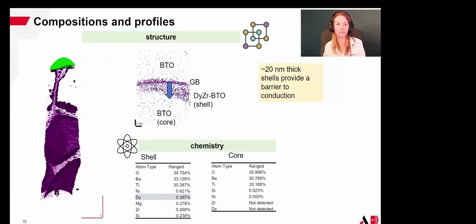We can also look at the approximate size and uniformity of this shell, and we find that it's kind of a different phase. It's still BTO, but with the significant presence of both dysprosium and zirconium. This forms about a 20 nanometer thick shell, which is sufficient, if we look in the literature, to provide that barrier of conduction from core to core in our MLCC materials.